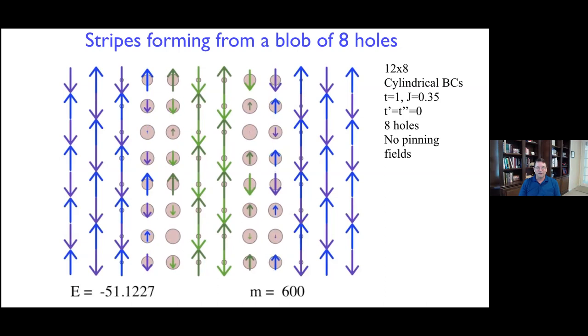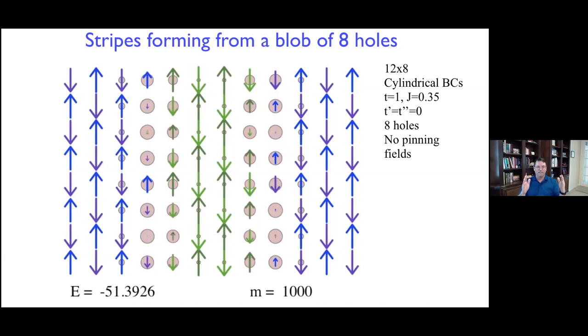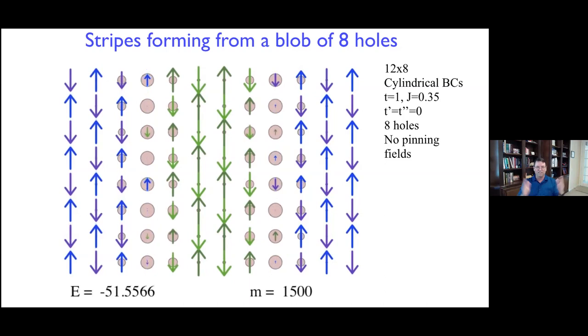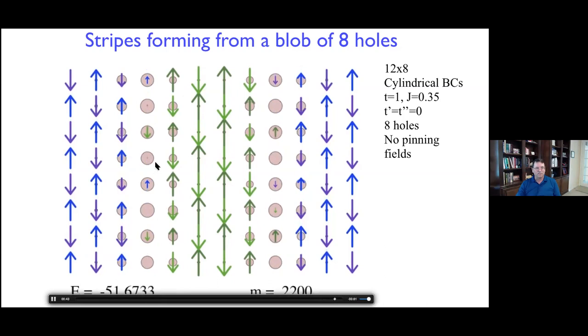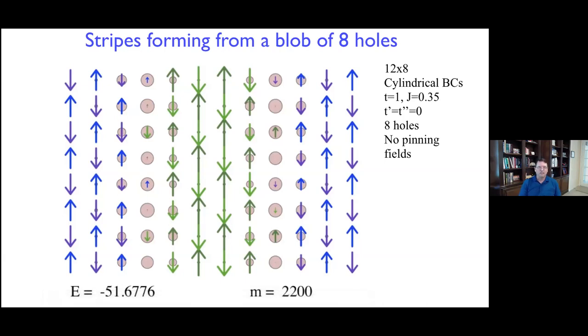So we see a left stripe and a right stripe, and they slowly push apart and evolve. Sometimes they look like site-centered stripes, sometimes they look like they're centered on the bonds. They gradually separate. In all these plots, the diameter of the circles is proportional to the hole doping. The color coding of the arrows shows you the different phases or domain walls of the antiferromagnetism. An up spin on an even site is one color, and on an odd site it's another color. And this is all automatic.